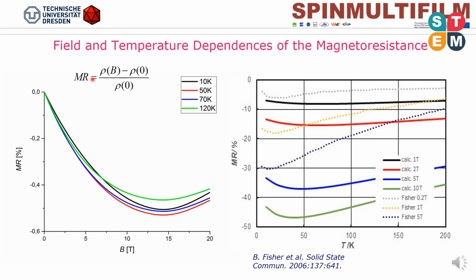The magnetoresistance is defined as a resistance change when applying a magnetic field relative to the field-free value. This figure illustrates the magnetic flux density dependence of the magnetoresistance MR. The obtained negative values are similar to the ones obtained for high-temperature sintered strontium ferromolybdate ceramics. The predicted absolute values increase with increasing magnetic flux density. The decrease at very high magnetic fields is an artifact of the model attributed to the termination of the series expansion of the field dependence of the tunneling barrier.